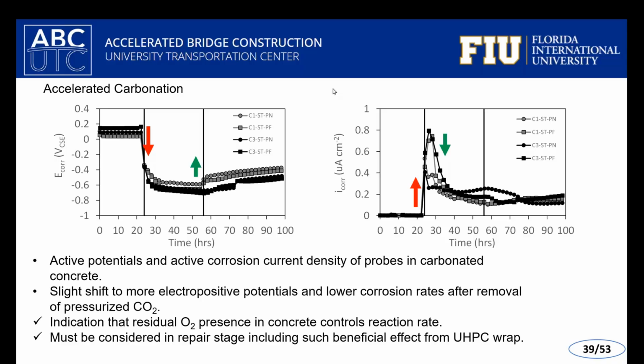These two graphs show, with the red arrow, the time when it carbonated. We placed the pressure vessel with the CO2 gas, and it diffused through the system for the first 20 hours or so. It got to a point where it became sufficient to activate the steel directly underneath that pressure vessel. We know active corrosion developed because we have that drop in half-cell potentials from more positive to highly negative potential, more negative than about minus 300 millivolts versus the copper sulfate electrode, and the rapid increase in the corrosion current density. So this is how we verified that corrosion indeed developed underneath that system.